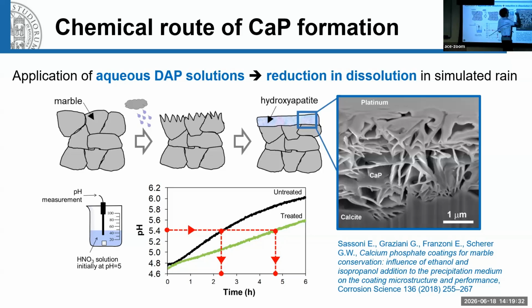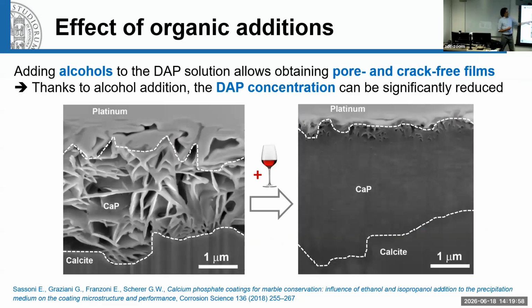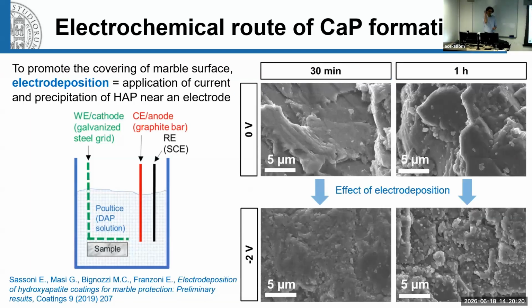Why? We performed some FIB observation of these protective layers, and what we found was that the barrier layer is quite porous. Because of that, it cannot provide a very effective barrier, because rain, acidic rain, is able to pass through the porosity and corrode the substrate. By performing some further research, we were able to densify these protective coatings. As you can see here, we found that by adding a little alcohol to the solution, it's possible to obtain a much denser coating, which is able to provide a much higher protective action, because in this case, rain cannot reach the substrate anymore.